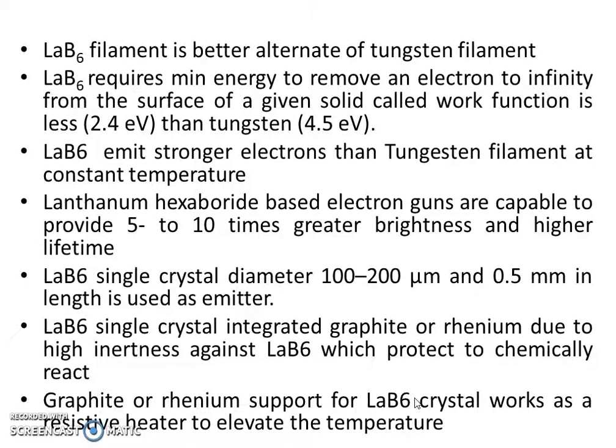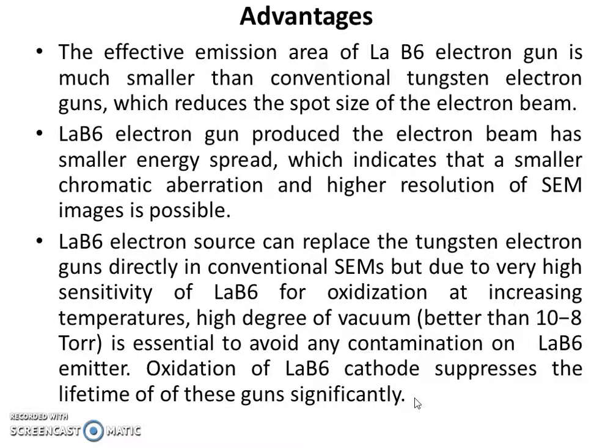A LaB6 single crystal of 100 to 200 micron diameter and 0.5 mm in length is used as an emitter. Graphite or rhenium support for the LaB6 crystal works as a resistive heater to raise the temperature to the desired level. Advantages: the effective emission area of the LaB6 electron gun is much smaller than conventional tungsten electron guns, which reduces the spot size of the electron beam. LaB6 electron guns produce an electron beam with smaller energy spread, which indicates smaller chromatic aberration and higher resolution of SEM images is possible.